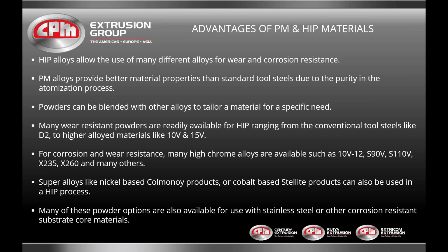Many wear-resistant powders are readily available for HIP, ranging from conventional tool steels like D2 to the higher alloyed materials like 10V and 15V. For corrosion and wear resistance, many high chrome alloys are available, such as 10V12, S90V, S110V, X235, X260, S115V, and S125V are other products. There's many on the market already that can be used. And the super alloys like the nickel-based Colmonoy products or cobalt-based products can also be used in a HIP process. Many of these powder options are also available for use with stainless steel or other corrosion-resistant substrate core materials.